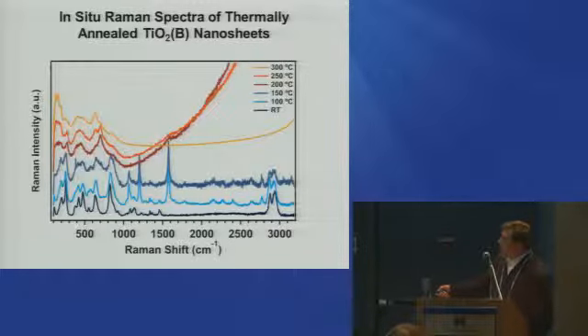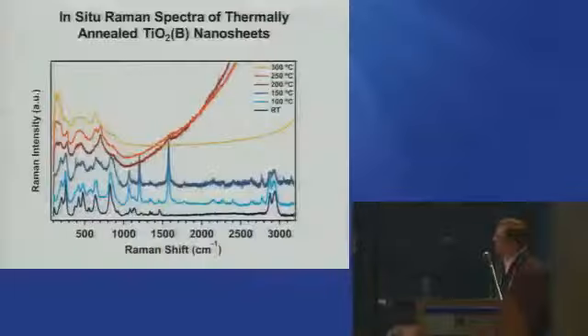You then get decomposition of the ethylene glycol and molecular fluorescence that's formed due to the capping ligand on this nanosheet that controls this particular morphology. And then as you get hotter, to about 300 degrees, you can see this main peak that's missing down here; that's the anatase signature. Okay, so interpreting this, of course, this is a small analytical spot size, about 2 microns, but it's still not good enough to really recognize whether you have intermixed phases and what would be the phase transitions between these particular materials thermally.